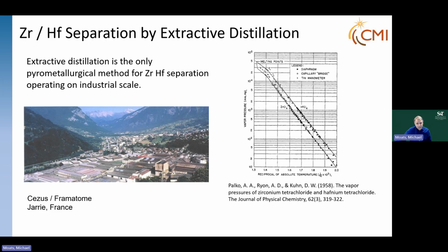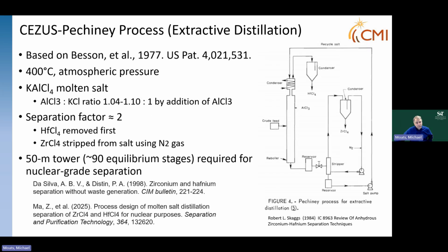There are systems based purely on this, where you just heat this up and you can get distillation differences based on vapor pressure. It takes a lot of stages, and so it's not been commercially utilized. But what is utilized in the extractive distillation, and therefore pyrometallurgical, system is doing this through a molten salt. The key patent was Besson et al. in 1977. Basically the crude feed, the zirconium tetrachloride and hafnium tetrachloride that comes out of carbochlorination, is fed into a tower where molten salt, and here it says aluminum trichloride, but really it's an aluminum chloride, potassium chloride of a very specific ratio.